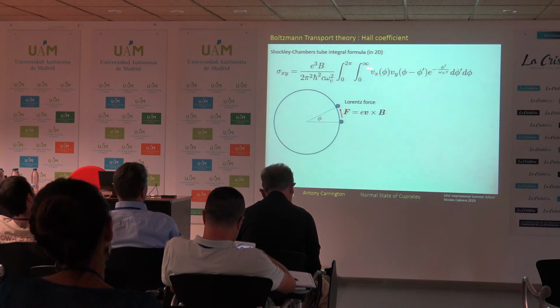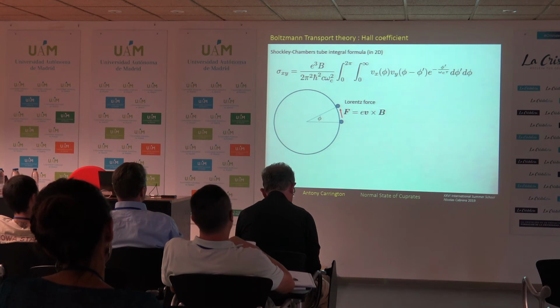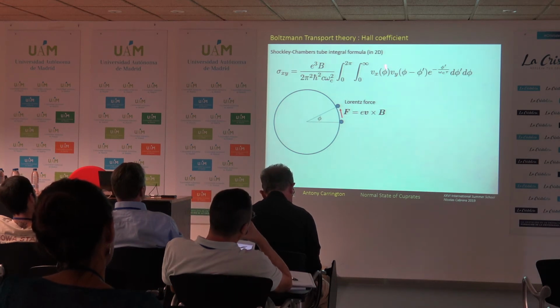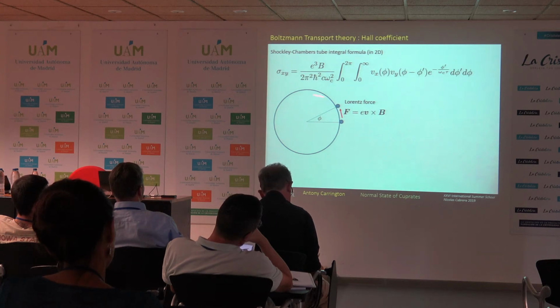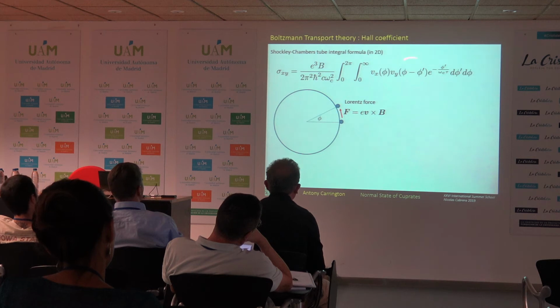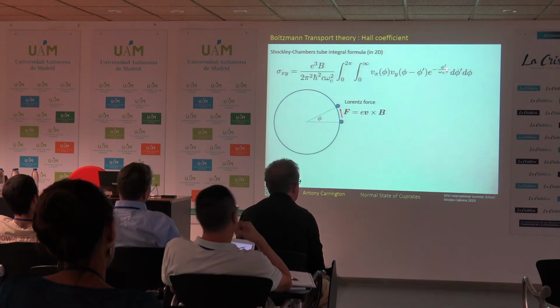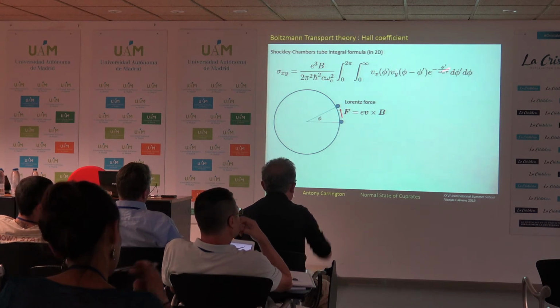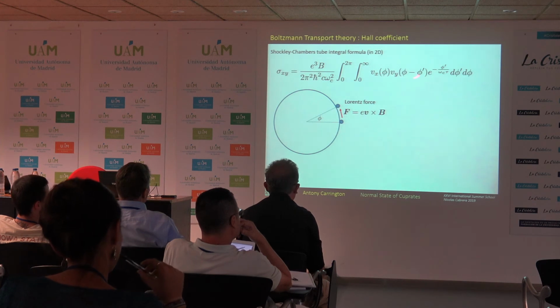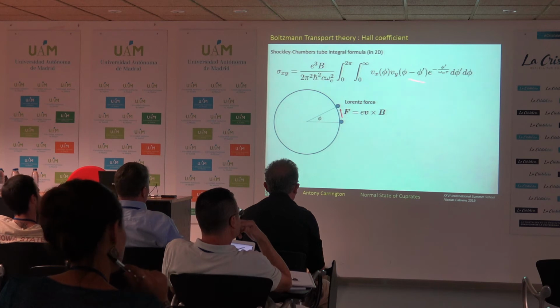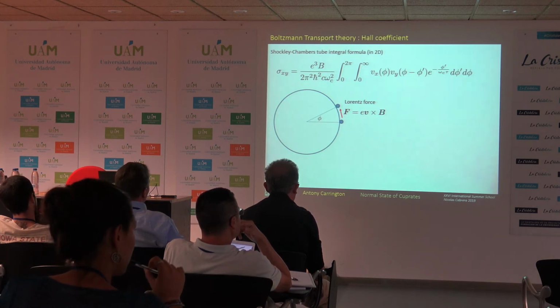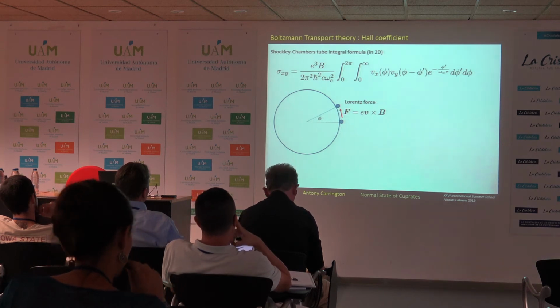So what you have is the Fermi velocity in the x direction at some angle on the Fermi surface phi, and then the y component of the Fermi velocity at some angle shifted by phi prime. So phi prime is how much we've moved around here with the magnetic field. And then we have this phase factor e to the minus phi prime over omega c tau, which basically says how much of this do we include in the integral. So if omega c tau is small, then this exponential term very quickly makes this integral converge. And so to first approximation, you can just linearly expand v_y and do the integral. That's what's called the weak field limit. And we'll get onto the high field limit in a minute.